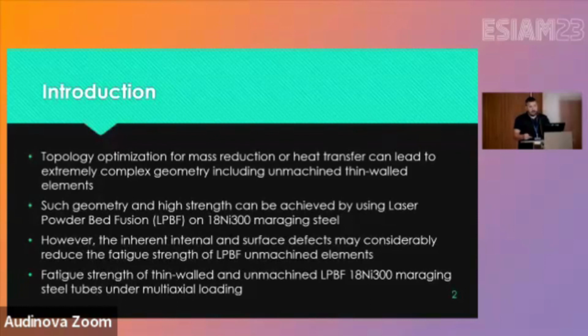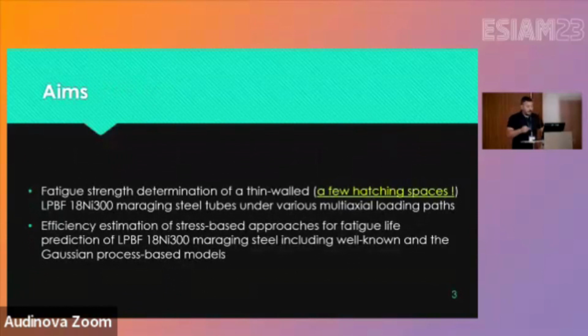So the fatigue strength of thin-walled unmachined parts obtained with additive manufacturing under multi-axial loading was something we wanted to take a look at. The fatigue strength determination of thin-walled, up to a few hatch spaces, Maraging steel tubes under various multi-axial loading paths was the aim of the study, and the efficiency of stress-based approaches for fatigue life prediction was also tested.